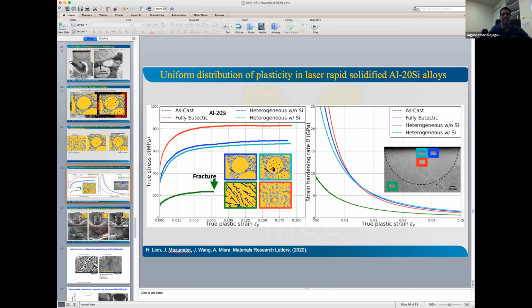But again, that is kind of more general. It's like how stable are these microstructures, right? You can make them, and how do they respond to stress or temperature changes and so on? So which one? The aluminum silicon? All of them actually. The ones that we showed for copper molybdenum all the way to this thing, right? Some of the copper moly stuff is deposited at high temperatures, so you would have expected that they will probably remain stable. But these aluminum silicon eutectics that you laser melt, how stable are those?